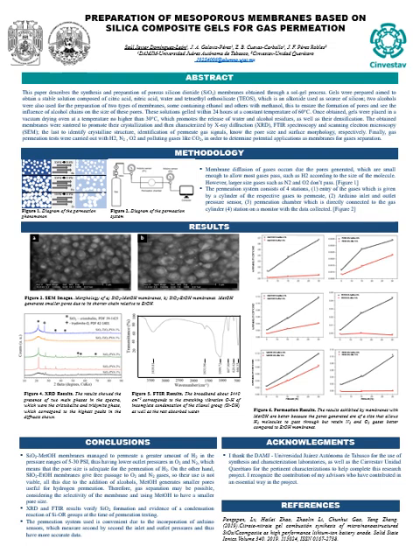The outlet pressure exhibits a correlation with elevated entry pressures. Conversely, under these pressures, the membrane will sustain a 90% permeation rate for hydrogen, whereas the passage of nitrogen and oxygen will be greatly restricted. This attribute renders the membrane apt for the segregation of gas mixtures tailored for specific objectives.